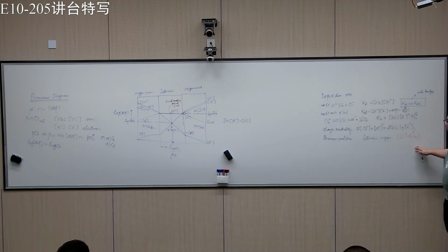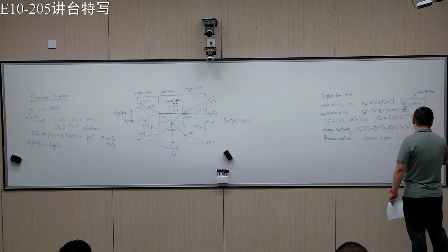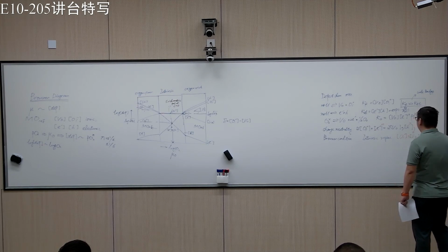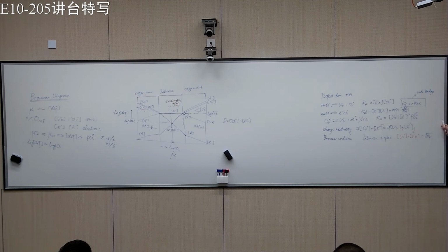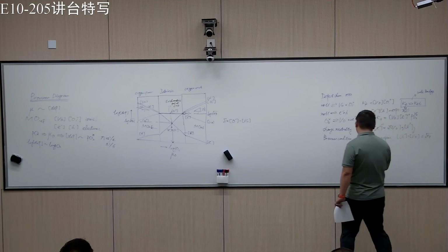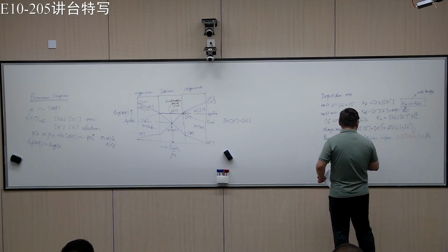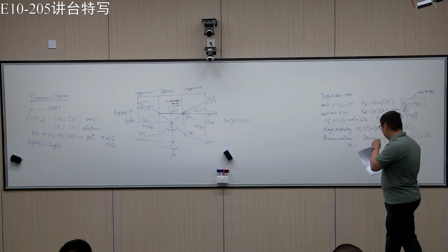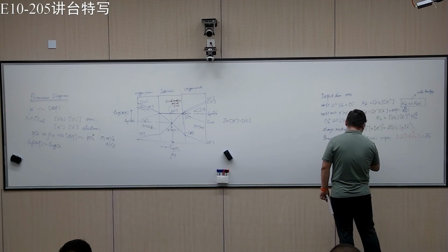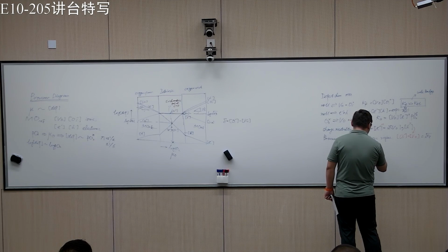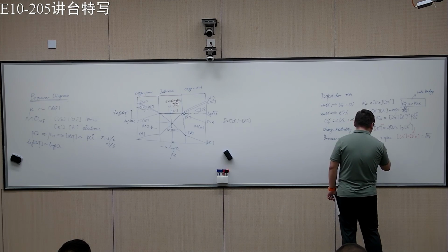We have the amount of oxygen interstitials the same as the amount of oxygen vacancies, the square root of KF. Okay. So essentially, we can plug into this equation. Basically, now we have KO the same as KF to the 1/2, then electron squared, then PO2 to the 1/2.